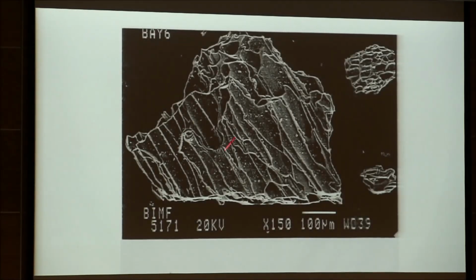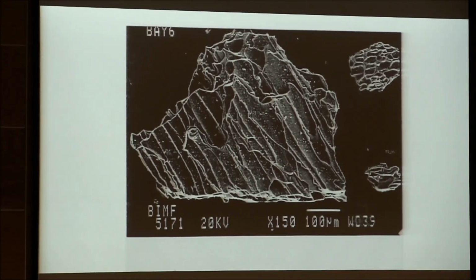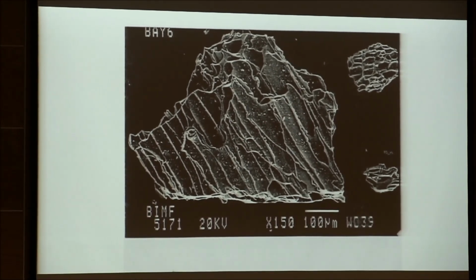We can even drive them to the most extreme state we know, which is so-called tube pumices. These are bubbles in rock which are 1,000 times longer than they are wide. It's incredible what nature gives us. We get eruptions which give us this, and also give us the other simple kind of porous rock. Why do we get these two things? We obviously have two different stress regimes in the eruptive system. And with this microanalytical technique, we can actually go in now, pick out these bubble walls, and see if they suffer a different thermal history than the simple rocks.